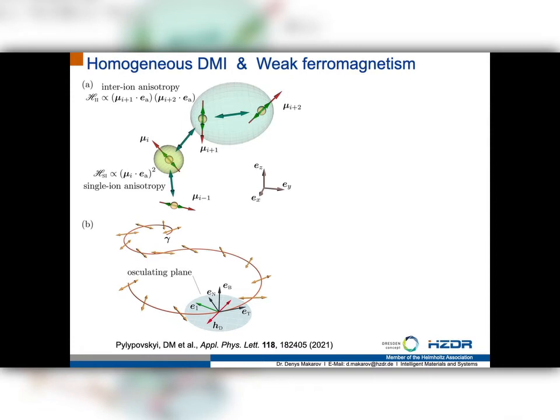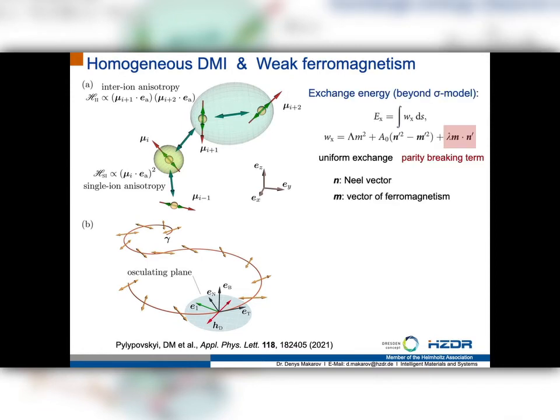For example, if you have inter-ion or single-ion anisotropies, you will be able to formulate the model beyond the sigma model which we discussed now, and in this case exchange will become a little bit more complex. You will have not only terms which are proportional to n prime squared, where n in this case is the Néel vector and m is the vector of ferromagnetism. You can see that the vector of ferromagnetism enters the energy and starts determining the properties of the system, and you have a very interesting term where n prime and the vector of ferromagnetism m are coupled together with a coefficient which is a parity breaking coefficient. The parity breaking term enters the energy functional of the system, and it determines homogeneous DMI and weak ferromagnetism.